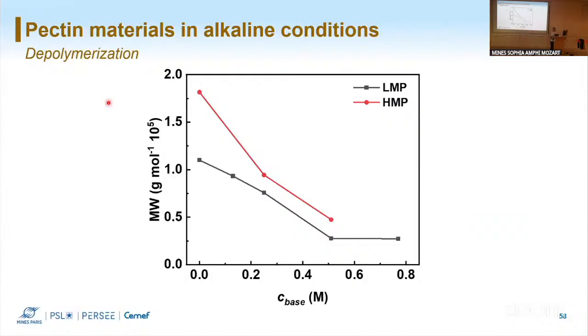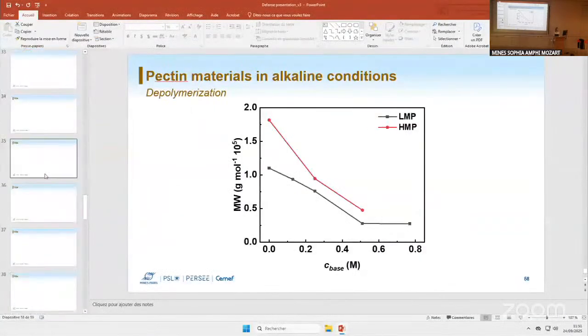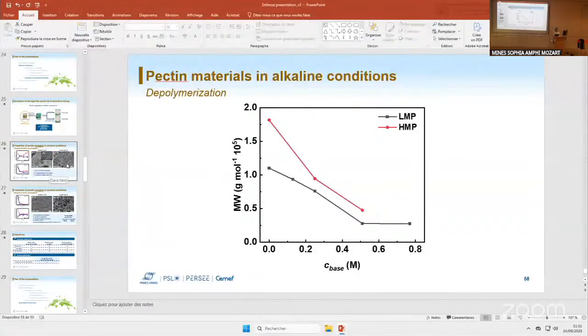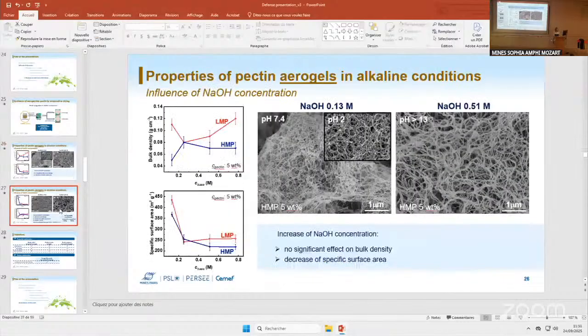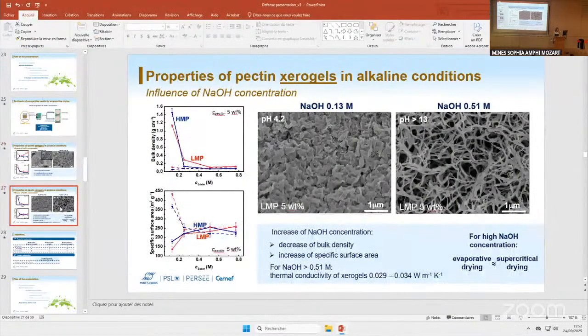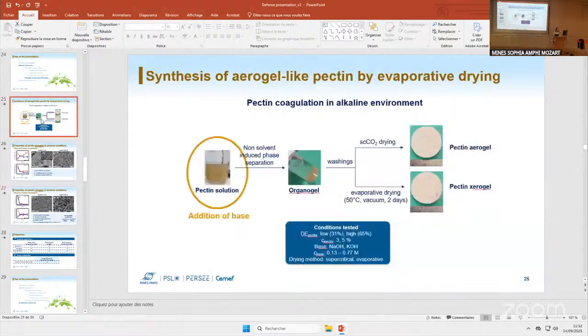When you talk about organogel, as you said, this is kind of it. This is precipitation. So for me, this is not a well controlled network. Especially, I have some question if you can come to a picture when you show the gel, on slide 25. Here the non-solvent is on the top, so that means that at some point you need to add alcohol, for instance, on top of a solution, because it's not a gel, it's a solution. Then you start to have a precipitation probably at the interface, and then you have progressive exchange of solvent, and for sure the network is maybe not so well controlled.